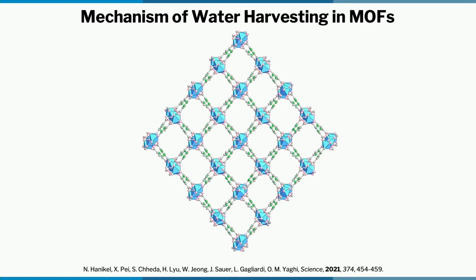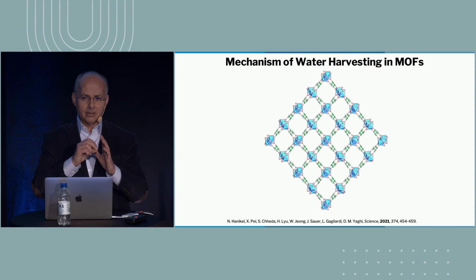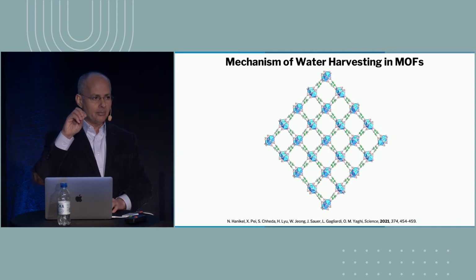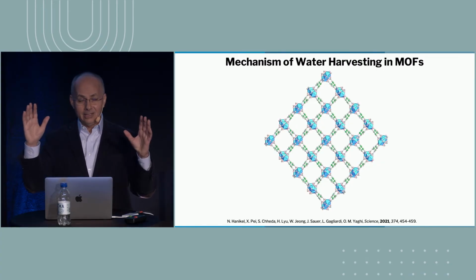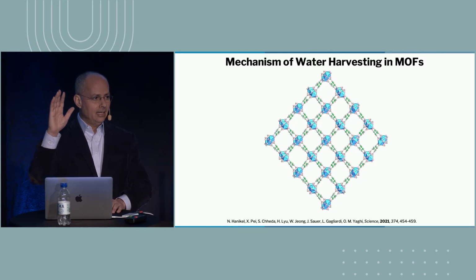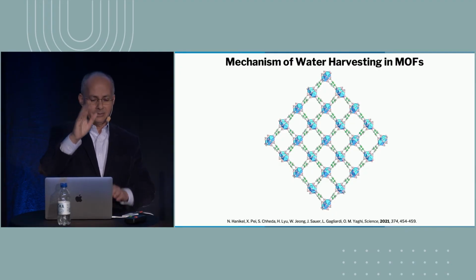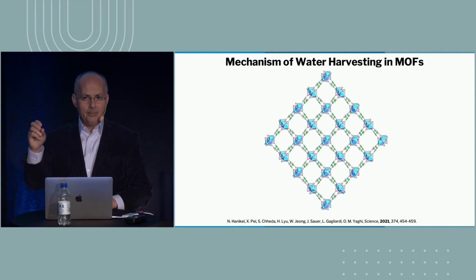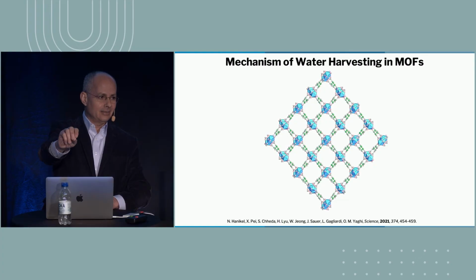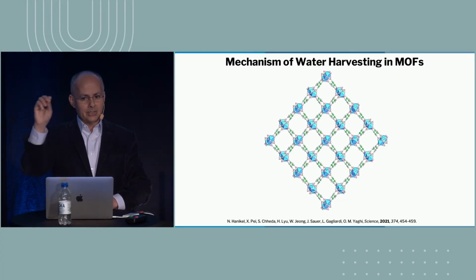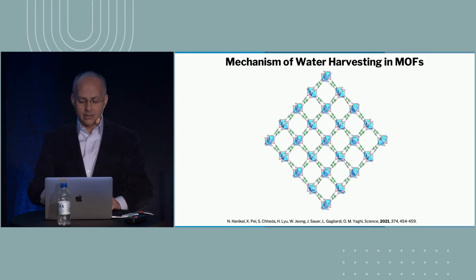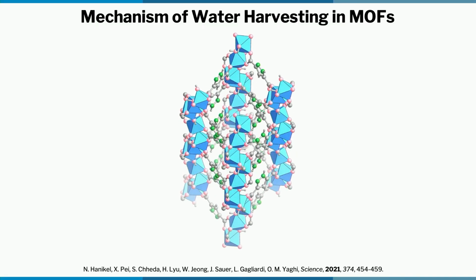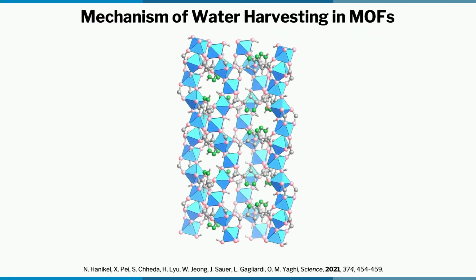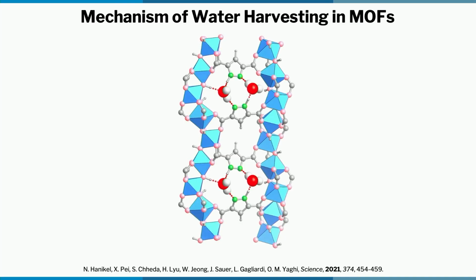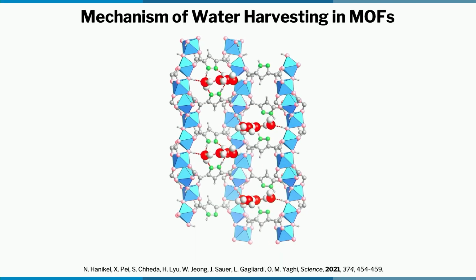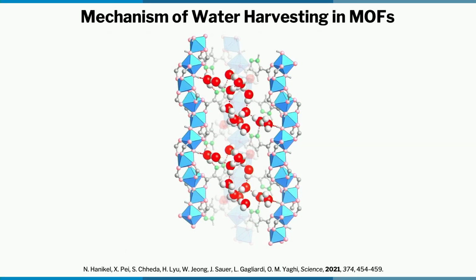What I want to show you now is a movie of where each water molecule is binding. But before that, if you're a water molecule moving through the pores and looking around, you're looking at a grid of hydrophilic and hydrophobic pockets, okay? Hydrophilic, hydrophobic, hydrophilic throughout each one of these pores. The first water molecules from air go to the hydrophilic sites, and when those are saturated, it bridges over the hydrophobic sites through water hydrogen bonding. And that's what you're going to see here. I'm going to take one pore out, cut it longitudinally so that you can see what's happening inside. Then you'll see water binding to the hydrophilic sites, and now start bridging over the hydrophobic sites because water is hydrogen bonded in the pores.